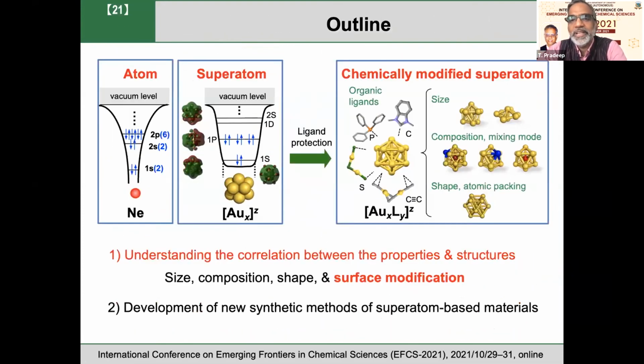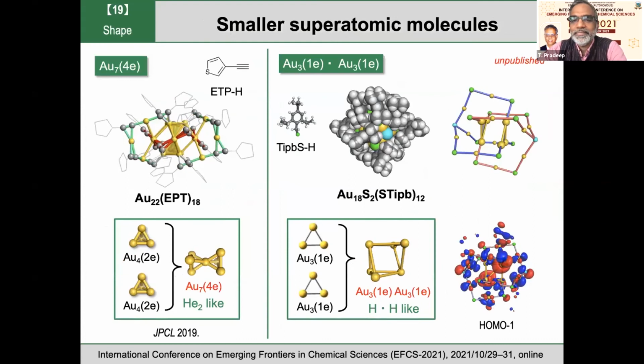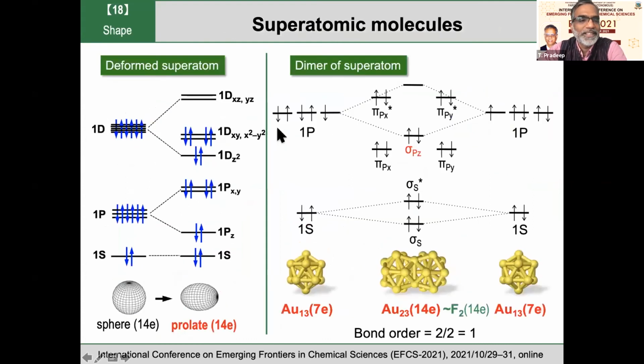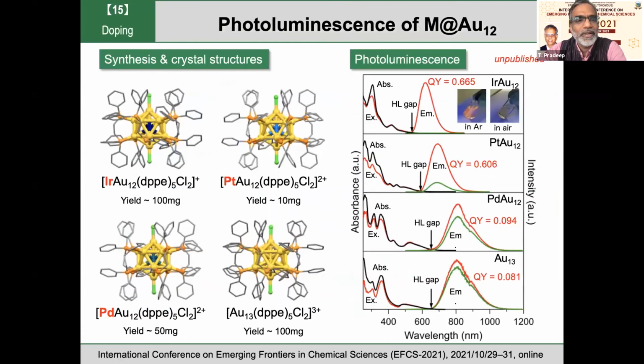So far we have no clear explanation, but by doping these elements, we know that the HOMO-LUMO gap gradually increases. So according to the energy gap law, the quantum yield can be slightly enhanced. So this is the only explanation we have. But there is no clear explanation for the doping effect of the photoluminescence quantum yield. We are all in a similar situation. To fully know it, we have big challenges.